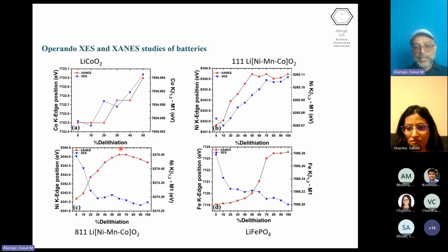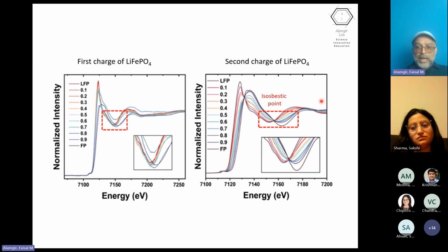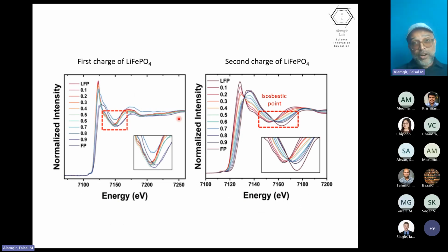So here's the extent of delithiation in 4 different battery chemistries, and we can see the extent of delithiation can be followed either by X-ray absorption, which is already known and a lot has been done, but also by X-ray emission, which is a new technique, you might say, for characterizing batteries. Just to show you the level of detail that we can get from X-ray absorption at our instrument, here's the first charge versus the second charge in LFP, or lithium iron phosphate materials, and you can see that there's quite a big difference between the first charge set of data and the second charge set of data.